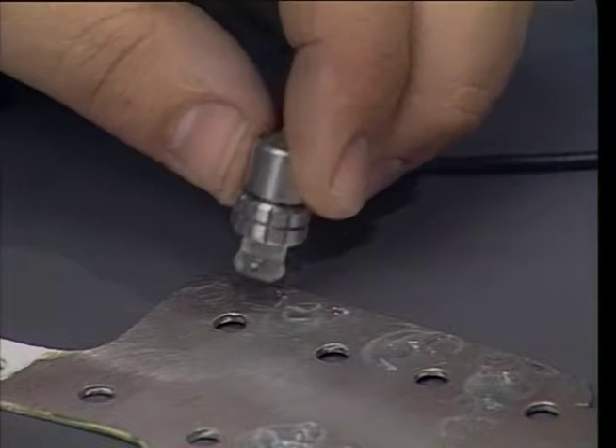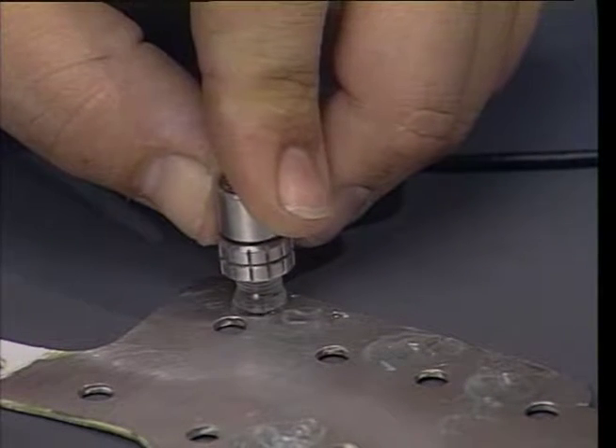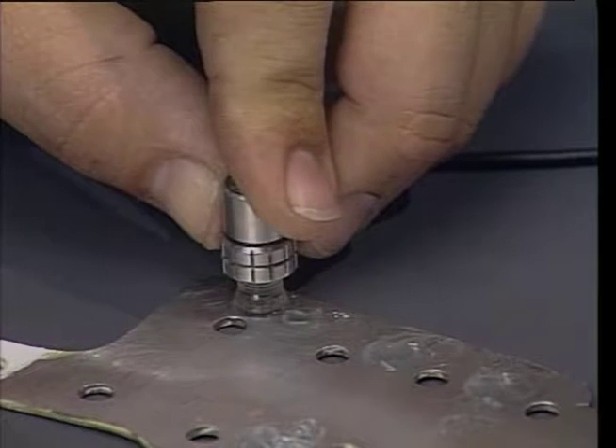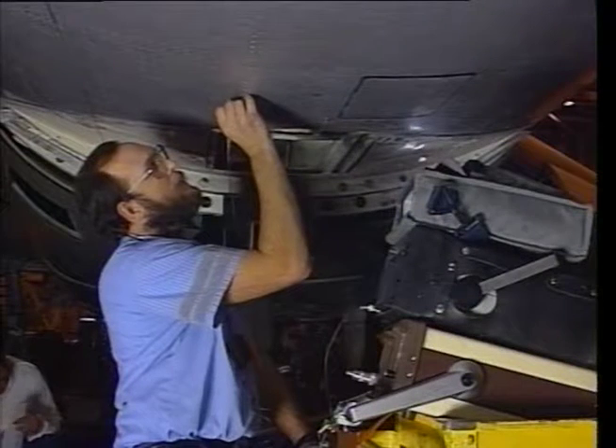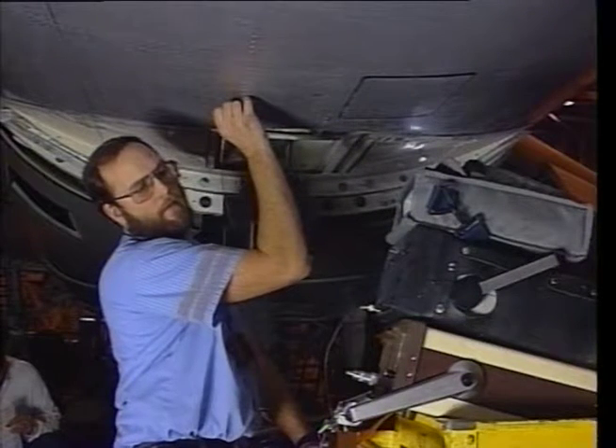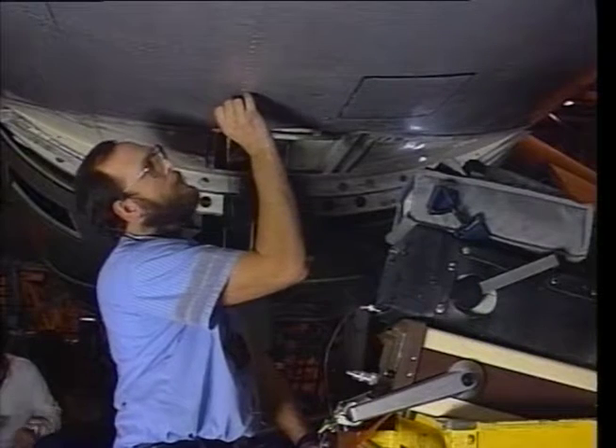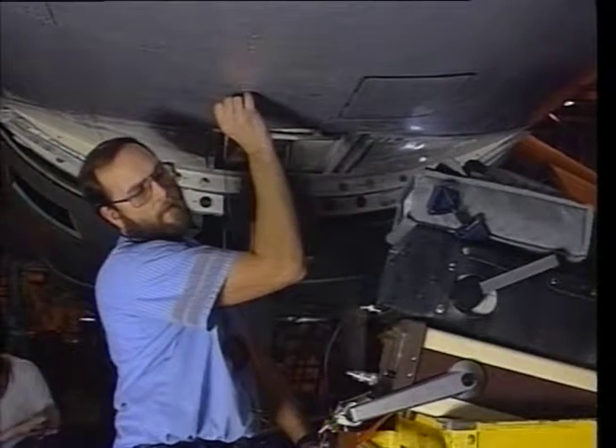Because the smallest crack or separation will affect echo return, the ultrasonic test here detects an otherwise unseen delamination flaw within this alloy skin. The reliability of ultrasonic thickness testing is compromised when the surfaces are not smooth. Pitting and corrosion, even paint, can cause the ultrasound to be scattered and attenuated.